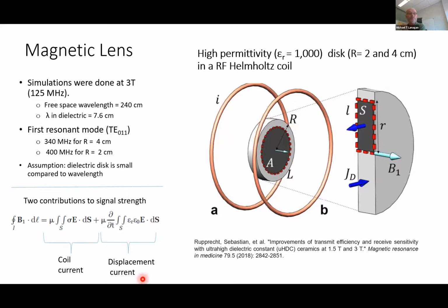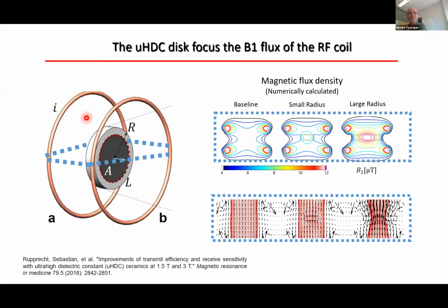So what we can then do is look at the relative contributions of the coil current and the displacement current for various disks that have certain permittivity values and dimensions. So here we can look at, for example, resonators of disks. We're actually below the resonant frequency, so it's not really, in this case, a resonant response. We're just looking at the displacement current below resonance. And here I'll show what the magnetic field looks like for a free space wavelength at 3 Tesla, which is 125 megahertz. That's in this slide here.